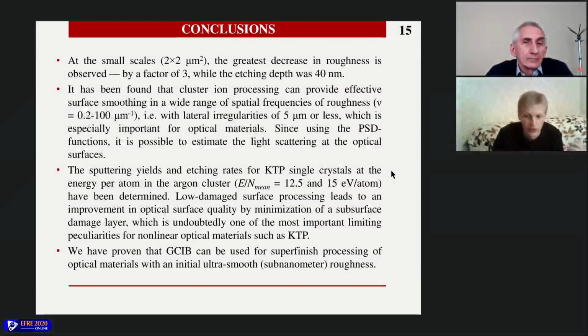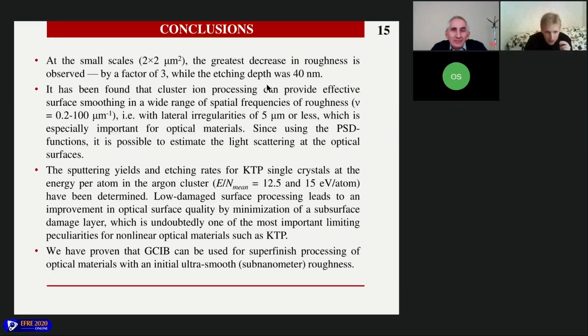And in conclusion, at the small scales, we see the greatest decrease in roughness, by a factor of 3, but the etching depth was only 40 nanometers. And it has been found that cluster ion beams can provide effective surface smoothing of lateral irregularities of 5 micrometers or less.